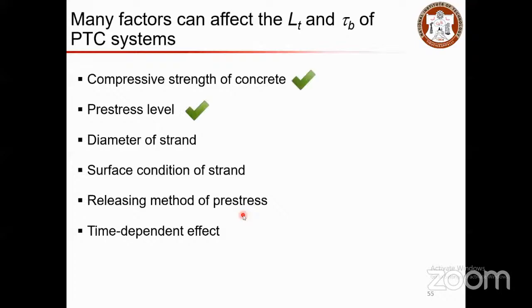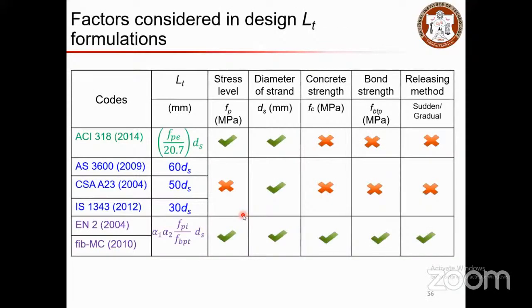But when you consider the code recommendations, not all the factors are being considered, especially in the Australian, Canadian, and Indian codes. So that talks about the transmission length with respect to only the diameter of the strand. So if you change the concrete strength, or if you change any one of these factors, you will end up having the same transmission length, but the real scenario is not the same. So using these equations is not appropriate, whereas the Eurocode and FIB code give you the scenario of all the factors being considered which would influence the transmission length.